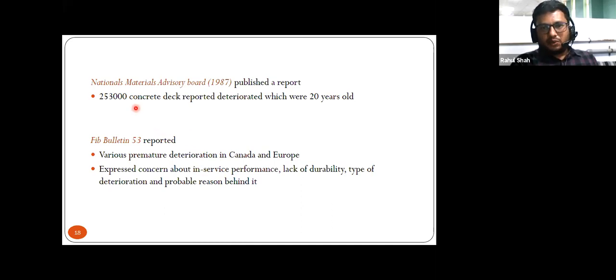National Material Advisory Board in 1987 published a report. They reported around 2,53,000 concrete decks which had deteriorated, which were only 20 years old. So this 20-year-old concrete is not older concrete. It is quite young, we can say, because we assume 100 years as a design life. FIB bulletin also reported various premature deterioration in Canada and Europe. It expressed concern about the in-service performance, lack of durability, type of deterioration, and probable reasons behind it.